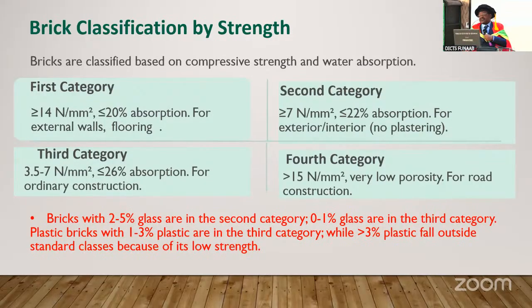The second category must have compressive strength greater than 7 and water absorption less than 22% for exterior and interior without plastering. The third category should have between 3.5 and 7 newtons per mm square and less than 26% absorption for ordinary construction, while the fourth category should have compressive strength greater than 15, very low porosity, this can be used for road construction.